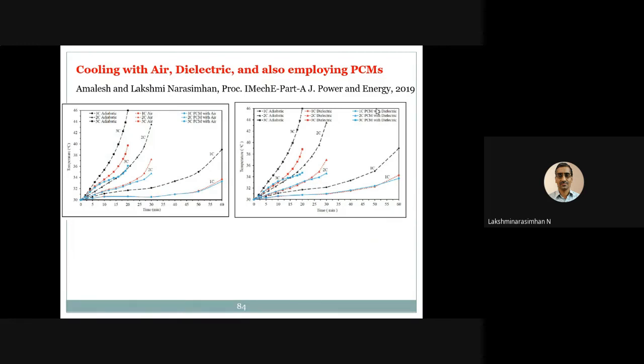And we have done calculations with air and dielectric and a combination of these, and using PCMs, all combinations, in a recent publication. We have tried with air alone, with PCM alone, with PCM and dielectric, and with PCM and air, and found out that PCM with the dielectric or PCM with the air is working fine. So we are able to find out that the blue color curves are representing the temperature. You see that at 1C operation, normally the temperatures are much less than 35 degrees centigrade.